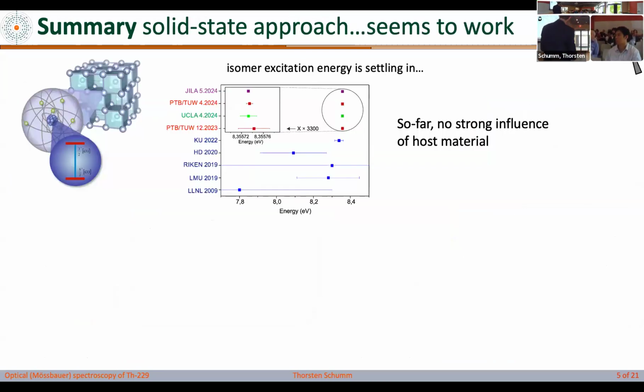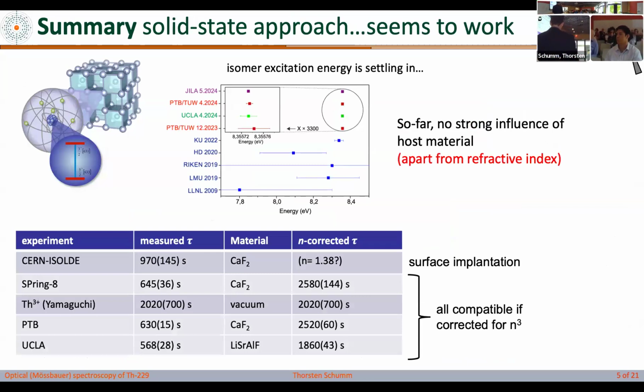From this perspective, it seems like everything is working, and Jim has shown a similar graph. We are narrowing down the energy, and so far it looks like the concept of having this nuclear two-level system sitting nicely in some material seems to work, because everything kind of coincides. If you look closely at the lifetimes that I have shown, there were some variations, but they come essentially from material parameters, because spontaneous radiative decay of whatever quantum two-level system has a lifetime which scales with the refractive index of the surrounding medium. And as I said, we have a decay within a surrounding medium. So that means the refractive index enters the decay lifetime.